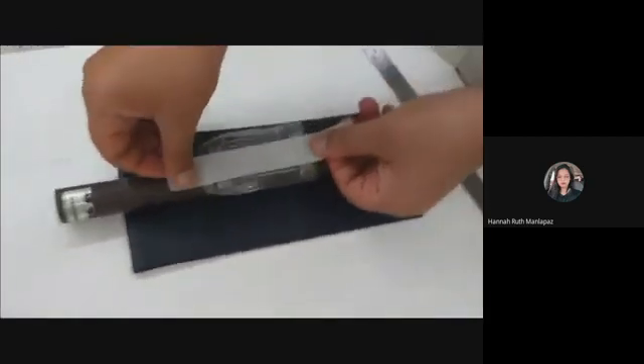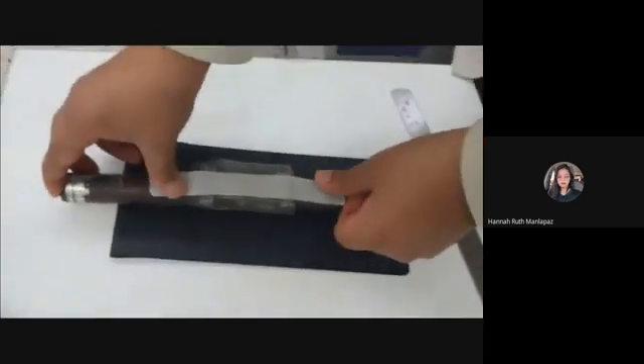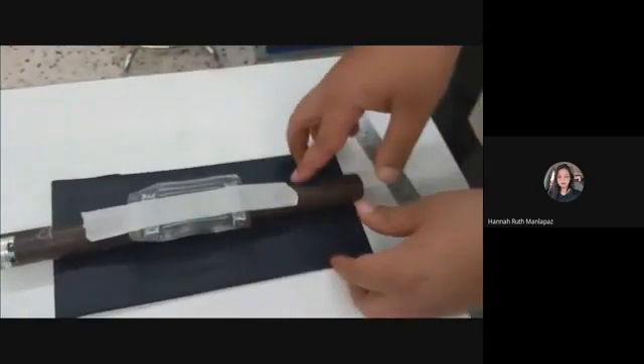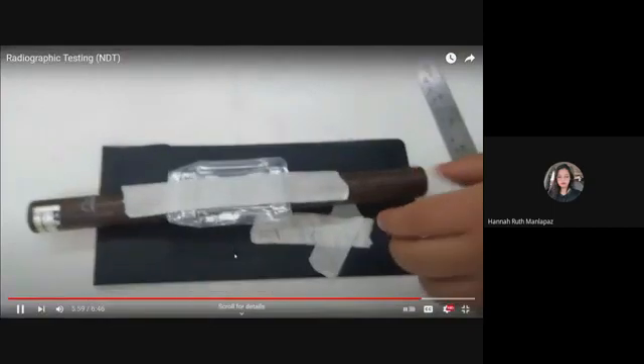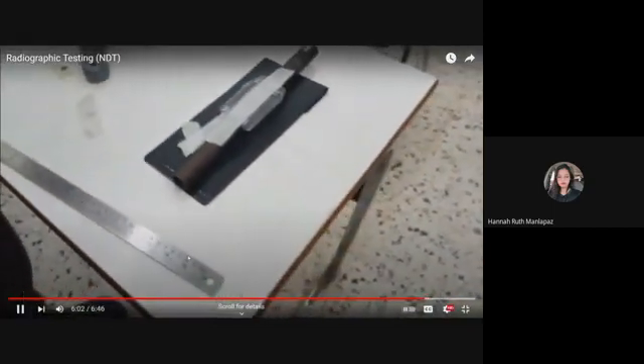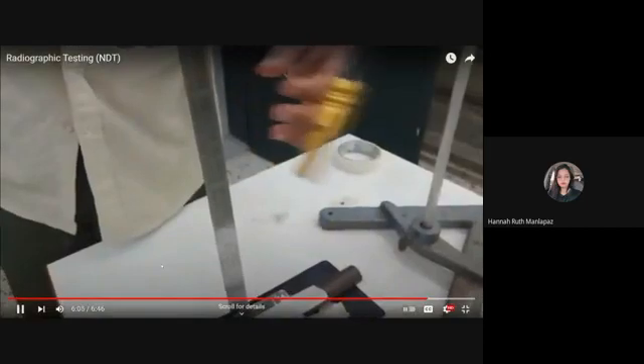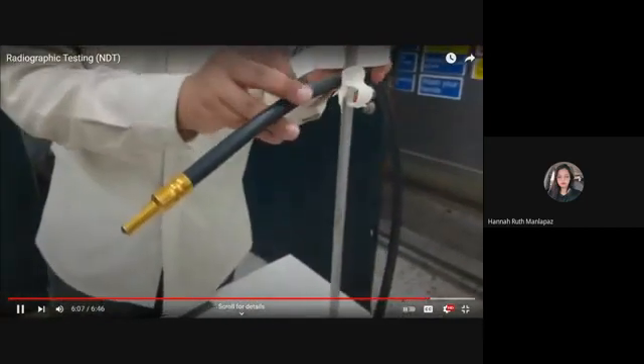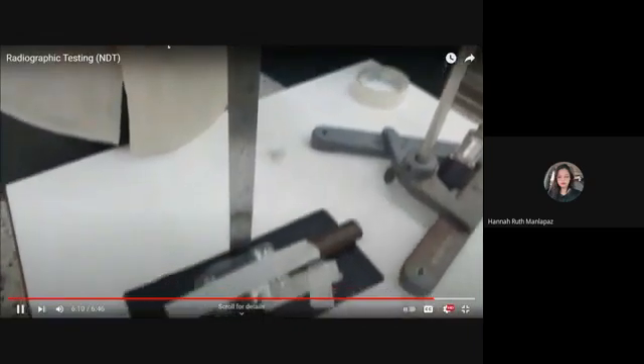Choose the appropriate IQI type according to the sample thickness of the same material as that of the specimen. IQI should be placed in a proper manner on specimen, i.e. source side and wires across the weld. Place the lead letters. Calculate the required geometrical unsharpness factors for both superimposed and elliptical techniques. Wrap the films around the welded pipe. Set the source at right angle with the film and weld seam using the magnetic stand and be careful to place the specimen at a proper distance. Calculate the exposure time by...